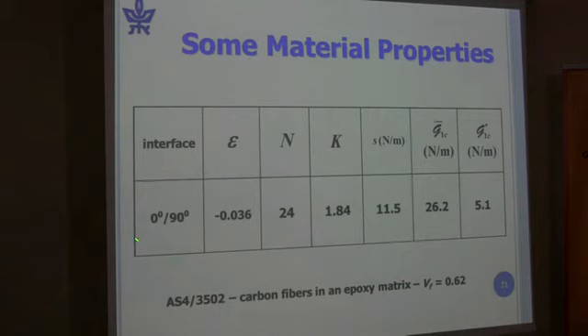Okay, so we're considering the 0-90 interface, and you will recall the oscillating parameter epsilon, which is very, very small. We had 24 tests. We calculated G1C bar to be 26.2 newtons per meter. The standard deviation is 11.5, which is rather high. And so with this K value that comes out of the statistics, we have a new value, G1C star, which is much lower. But now we only have a 10% possibility of failure in the safe zone.